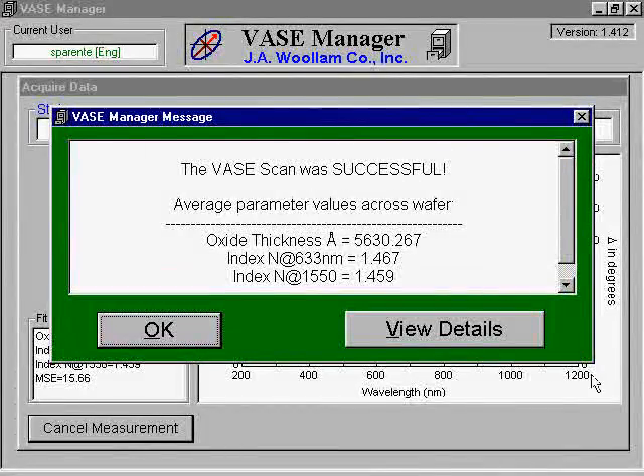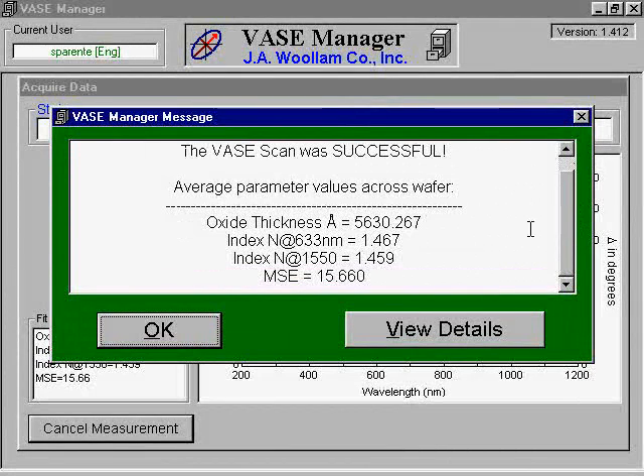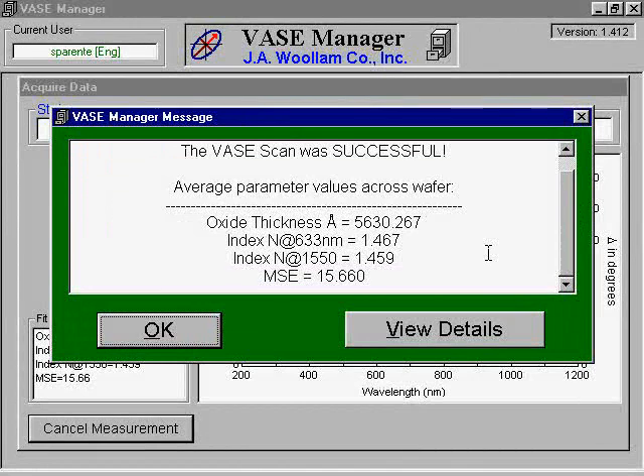The software should now have a summary of the results of the scan. The data provided includes film thickness, refractive index, and mean squared error, or MSE. The lower the MSE, the better your sample matches the model of the recipe selected prior to scan. An MSE value greater than 100 typically suggests that the analysis method did not accurately model your sample. You may wish to reanalyze your sample.